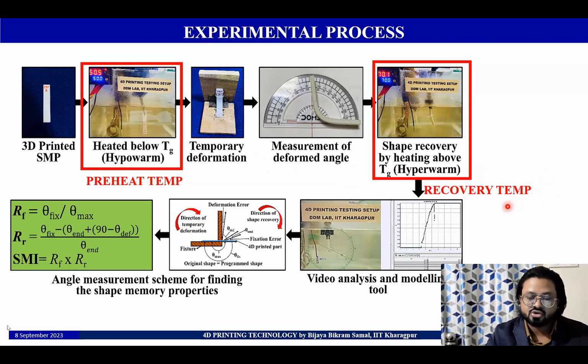So this recovery temperature also plays an important role, and if not chosen at the right value, then we can also end up with a recovery temperature which will reprogram the part, that is a temperature above the crystallization temperature. So we don't want to do that. That is why here we are optimizing the preheat temperature as well as the recovery temperature.